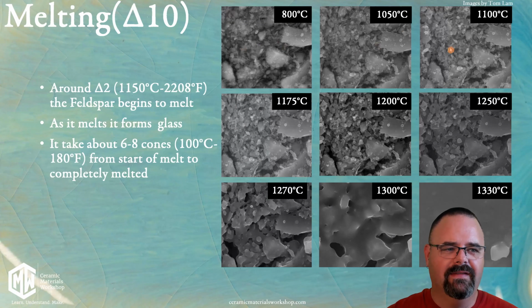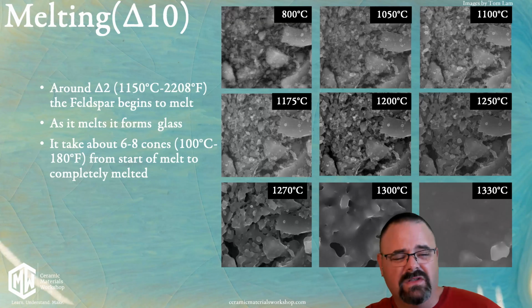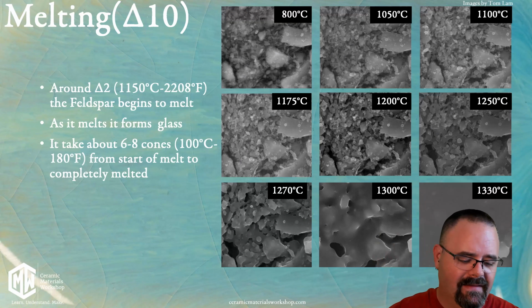05, and what we can see is that the glaze is barely melting. Not much is happening. We go up to 1,000, same thing. 1075, same thing. It's not until we get all the way up into about 1200 C and 1250, this is about cone 4 to cone 6, that things actually start melting. We can see the glaze particles or the clay particles coming together and the glaze now starting to form a melting homogeneous mass. Okay, then at 1270, 1300, and then at 1330, right behind me, as I move, it just looks smooth because that is the glaze completely melted.